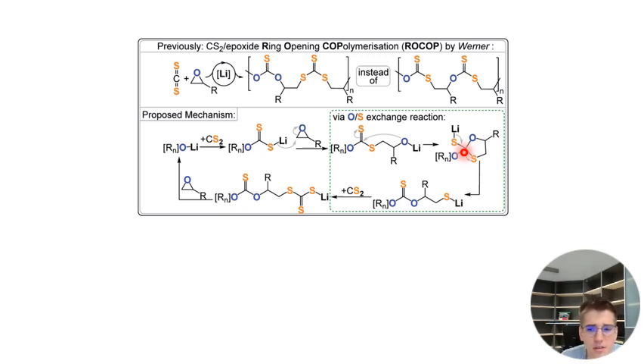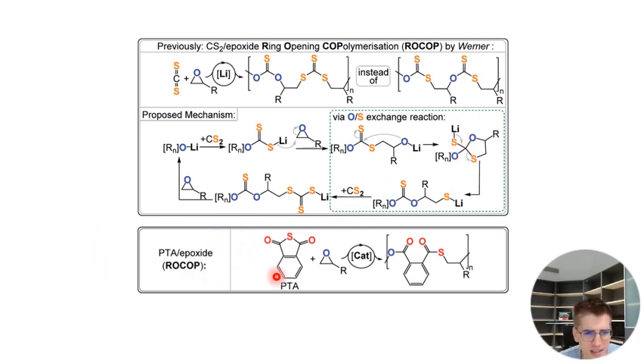So what is also relevant to the study was this other paper here, where they took a so-called thioanhydride with also propylene oxide, so where R is a methyl group. And depending on the catalyst, this works better or worse. Sometimes you get some errors in, but there were catalysts for which you form this alternating copolymer, right? So in effect, this here now in red is the ring-opened cyclic anhydride forming this thioester bond here, and then the blue oxygen and the rest of the organic part here comes from the epoxide that is being ring opened.